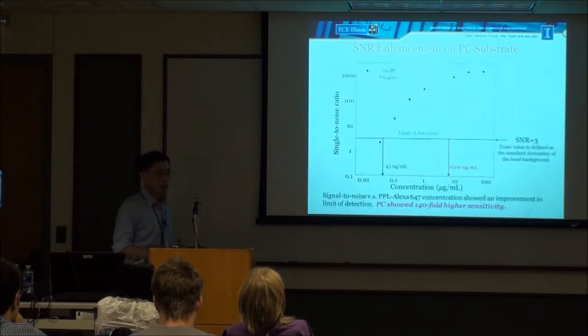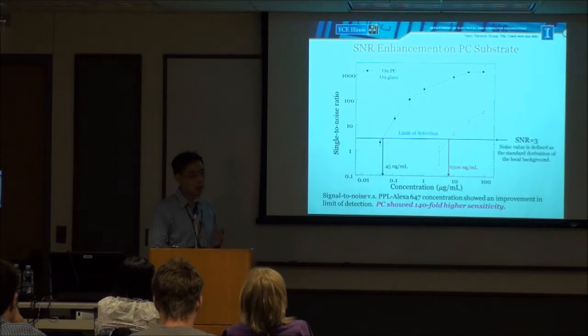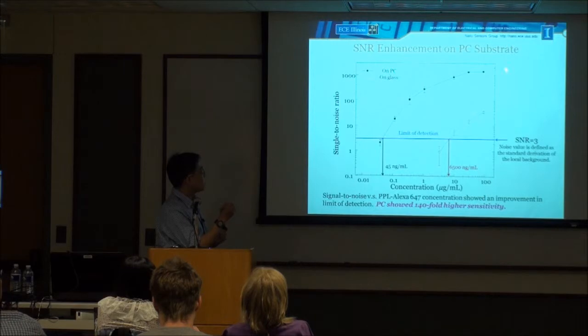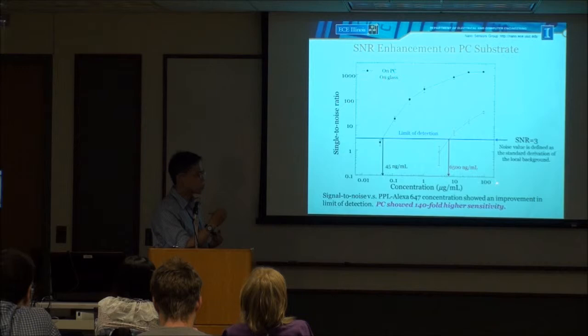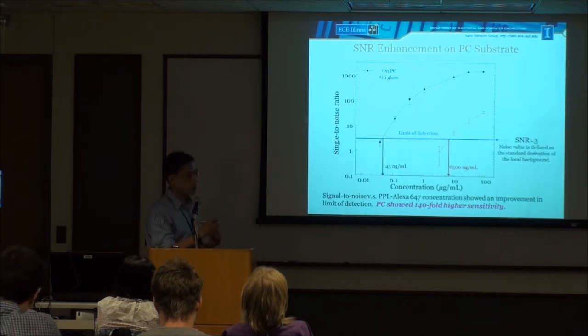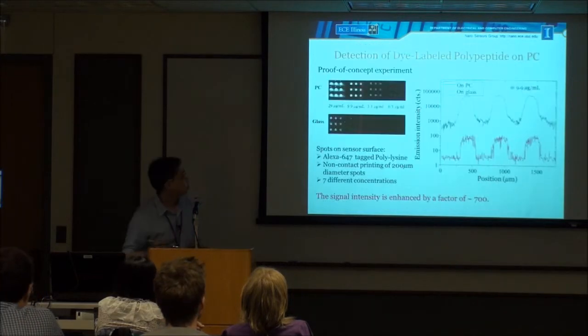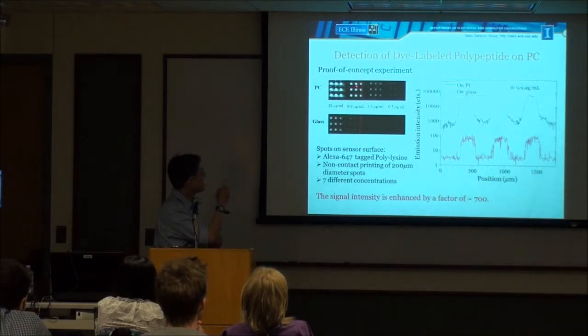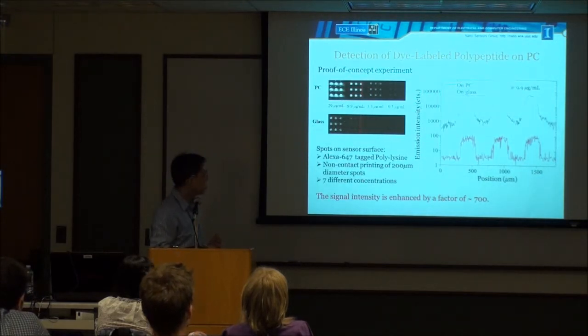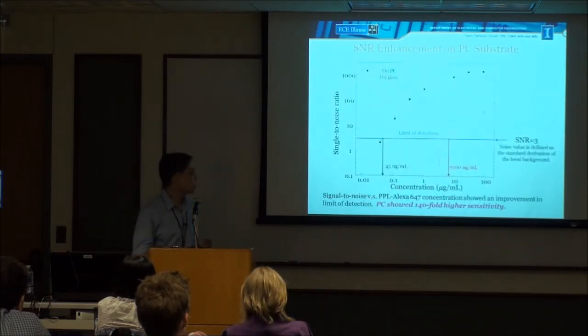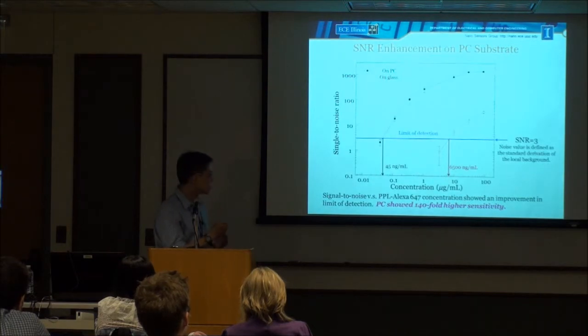The enhancement is big. However, it not only enhances the signal, it also enhances the background. So in this figure, we plot the signal-to-noise ratio in terms of concentration. The signal-to-noise ratio is defined as the signal over the noise of the local background, which is taken near the fluorescence spot. We plot a circle here to calculate the background intensity, and the standard deviation of that signal is defined as the noise.